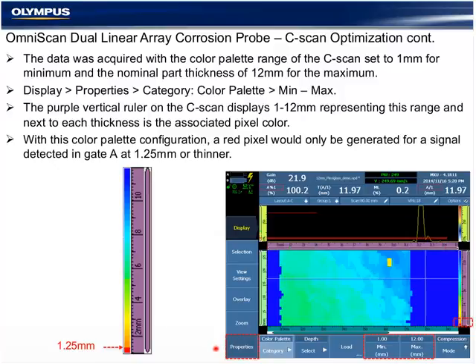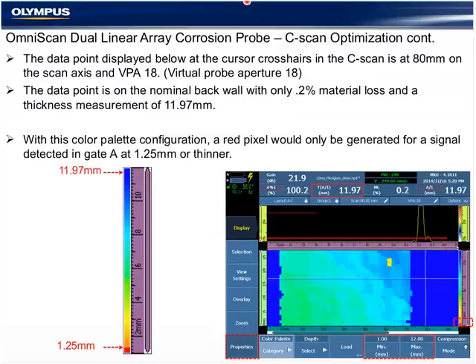With this condition, the color palette is going to generate a blue pixel here at 12 millimeters and a red pixel at 1.25 millimeters. As I adjust these numbers, or move this on the touch screen of the instrument, or with a mouse in OmniPC, the contrast of the C-scan is going to change to help me find the low points in the data or the problem areas of whatever I've just scanned.